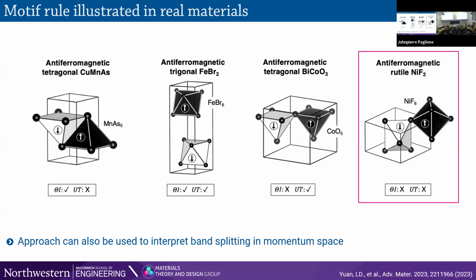But again, coming to altermagnetism, beyond thinking about just the band splitting, and this is maybe more common in the materials community, we should think about other screening metrics to decide what to pursue experimentally. If the material is highly defect sensitive, like you have anti-site defects that happen spontaneously, or there's a large concentration of oxygen vacancies, we're going to shift the chemical potential. Should we put a bound on what reasonable defect formation energies are in an altermagnet before we invest time in single crystal synthesis? Because it may be the best candidate, but it may take a lot of time to process that material to the fidelity you want. That's what we like to think about in my community, those other important aspects in addition to the fundamental physics. And they have to work somewhat hand in hand, because we want to make progress. I think you want multiple schemes.